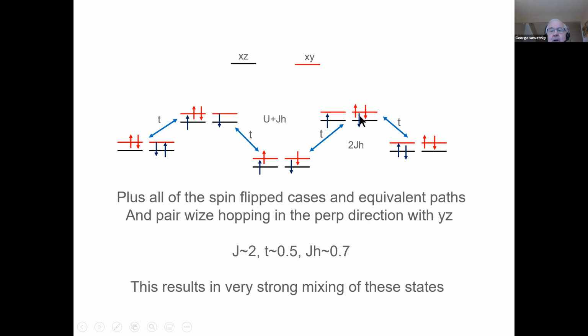Then you can hop this black electron from the XZ orbital to the left, giving it to the XZ on the left. Then you get this picture here. This is a spin 0 state, and this costs you twice Hund's rule. And you have many of these possibilities. You can go this way, but you can also flip spins around, making singlets or triplets. So you have many, many possibilities, meaning that you have a lot of degrees of freedom with degenerate energies of hopping. You can also have a spin on the YZ hopping in the other direction, also with the XY orbital. So again, you have more possibilities of hopping back and forth, plus all of the spin flip cases and equivalent paths and pairwise hopping in the perpendicular direction with YZ hopping.